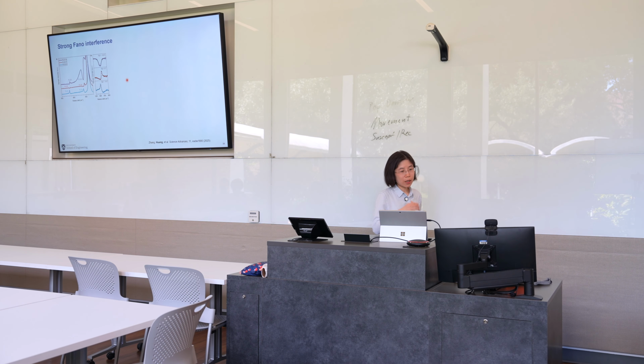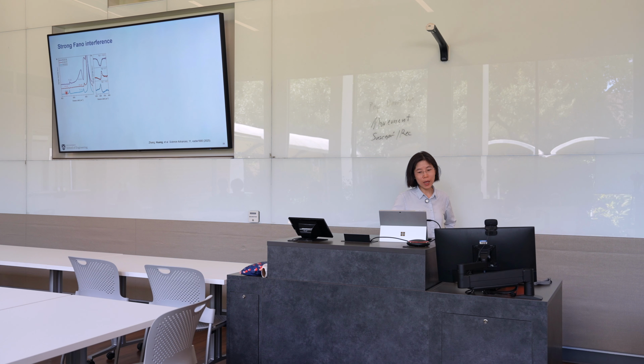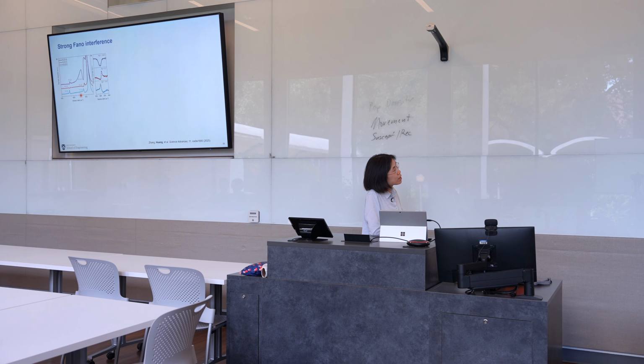Now, if we actually look closer at these samples, we can see different phonon patterns. In this spectral range, we have several modes of silicon carbide. They are called folded longitudinal optical modes, or FLO modes. There are several FLO modes, FLO 2, 3, 4, 5. There are 4 modes in this range. In some areas, we can see these FLO 2, 4 patterns.